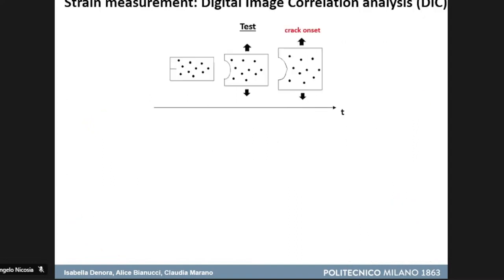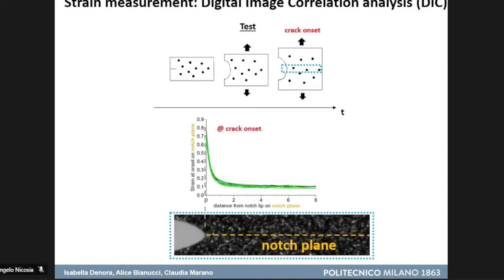Moreover, we are also interested in measuring the deformations, local deformations on the specimens. So we have a speckle pattern on the specimen, and tests were video recorded in order to track the displacement of this pattern. This analysis is called digital image correlation. So we have also measured the local deformations on the notch plane from the notch tip to the side of the specimen.